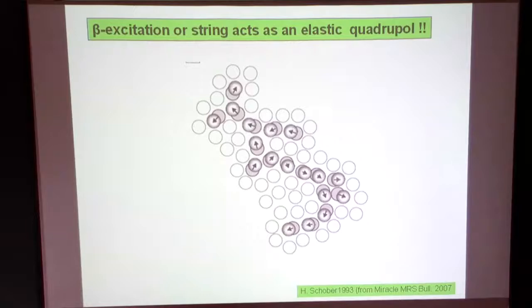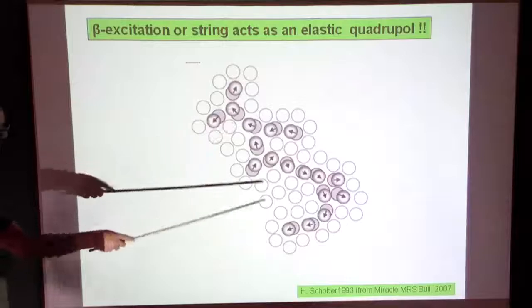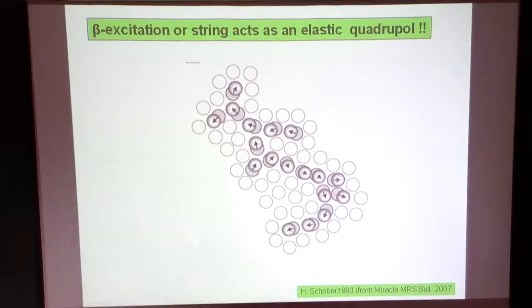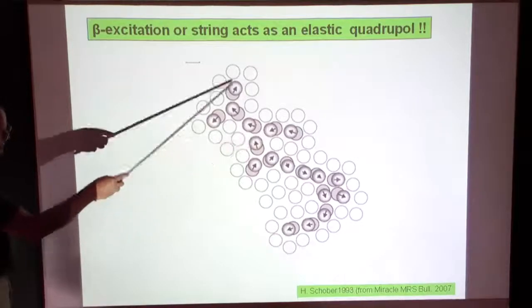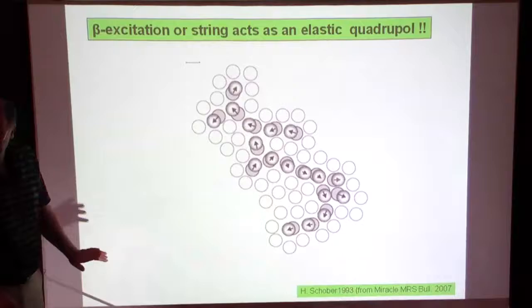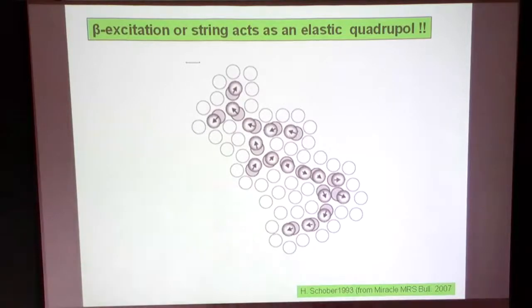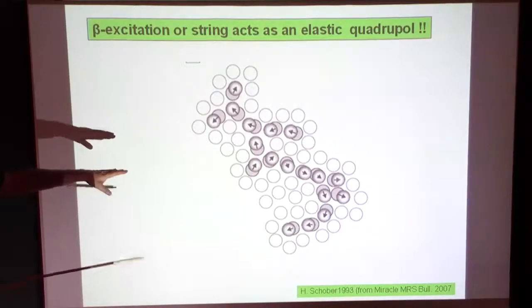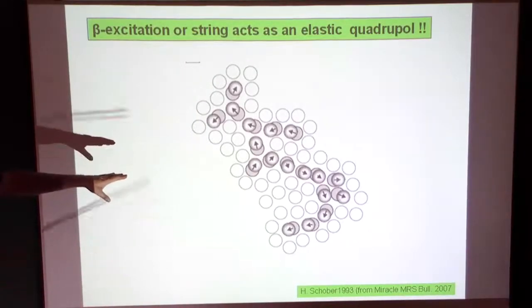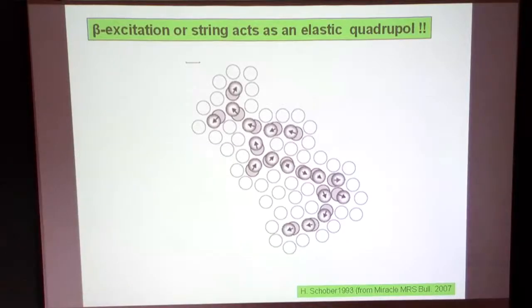This is from Helmut Schober many years ago, kind of a string which forms elastic quadrupole and is a 20 atoms rearrangement inside a certain matrix. And the idea is the following. If you talk about this microalloy now, you cut in between different parts of the string and form smaller segments, and they vibrate differently, and they are responsible for diffusion. People showed that diffusion constants depend on these kind of 20 atoms rearrangement also, and aging is also an issue